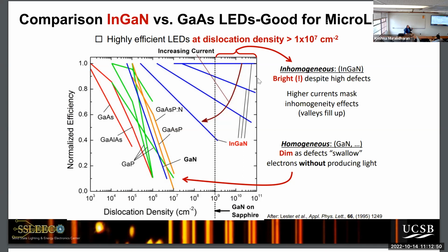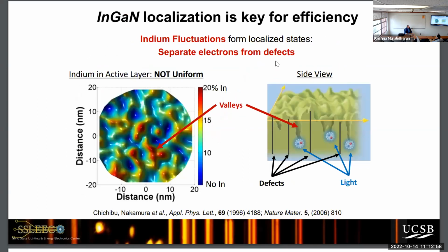He explained why adding indium to a crystal would make it immediately so bright, and particularly when you have so many defects. And the reason turned out to be quantum localization. This was something nobody had ever really seen before in light emitting devices. But when you add indium to gallium nitride, you don't get a uniform alloy. So a lot of people thought that was bad. It's actually a good thing. So you get an alloy which looks like this. And this is an atom probe measuring you from the top.